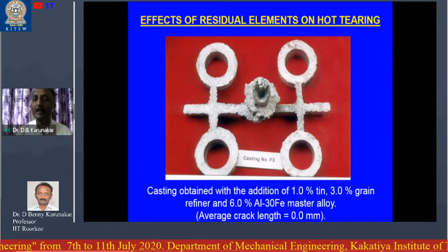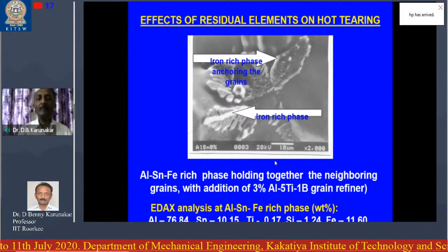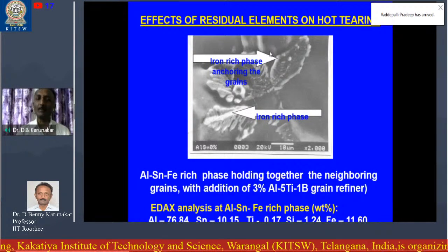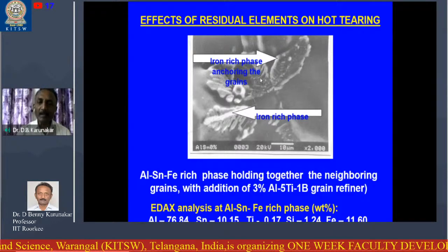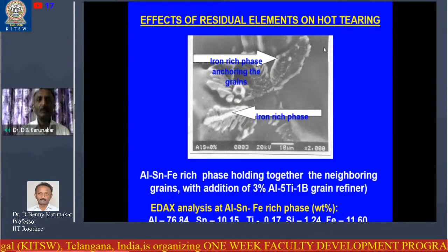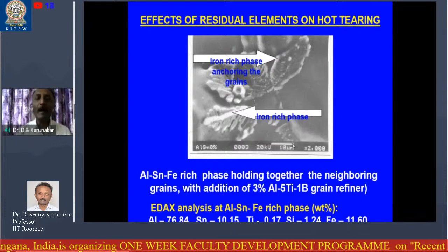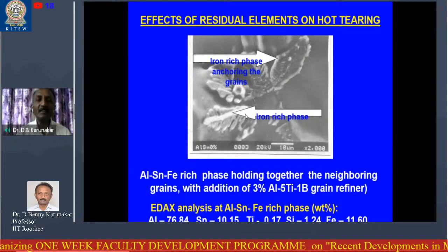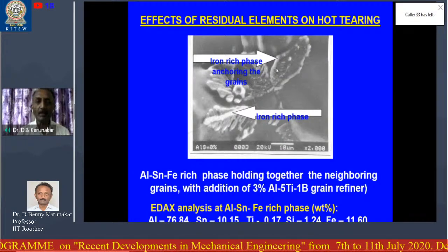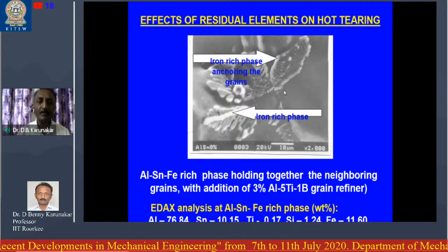When we investigated under the SEM, we found this kind of leaf-like structure at several places. You can see these are the grains, and a kind of leaf-like structure. When we analyzed it under the SEM, we found that these are iron-rich phases, because we had added the iron master alloy.